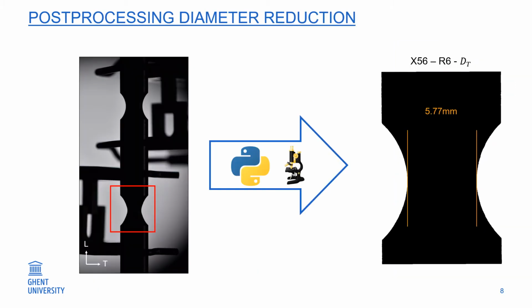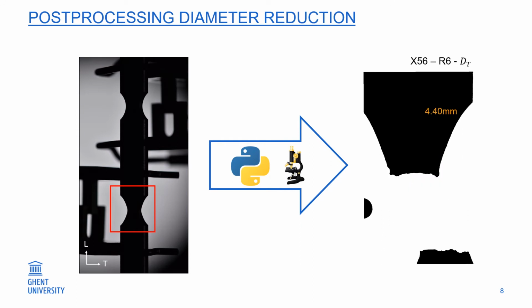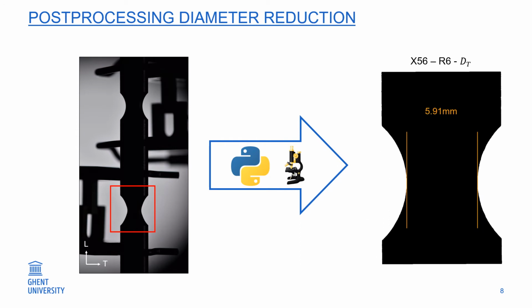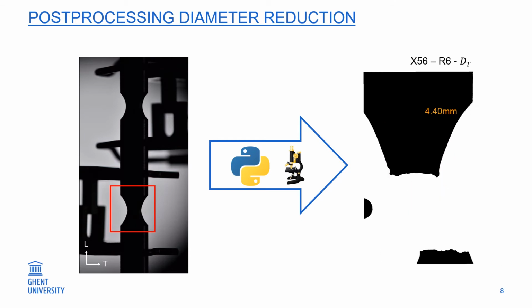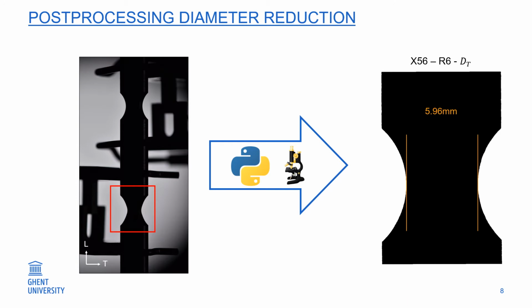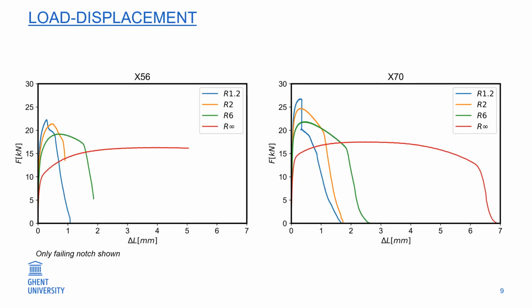After the test, the images can be post-processed by selecting a region of interest and thresholding the images using ImageJ and Python scripting. In this way, we have extracted the diameter evolution during the tensile test. The load versus axial displacement curves for both materials and all 4 geometries are given here.